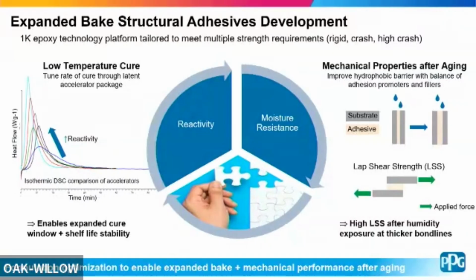And we're predominantly measuring that using lap shear strength. It's a fairly basic technique. I'm sure many of you are very aware, but essentially you apply a bead down with your two substrates. You apply a load across that, and you measure that failure mode, typically looking for a cohesive failure, so failure within your adhesive. And we want to maintain high lap shear strength after humidity exposure with these thicker bond lines, whether or not it's cured at 140C all the way up through the higher bake window.